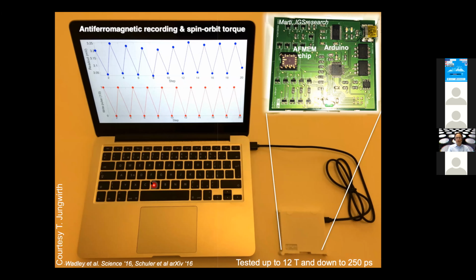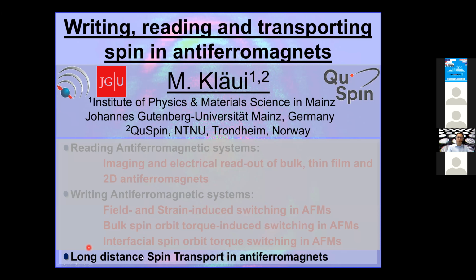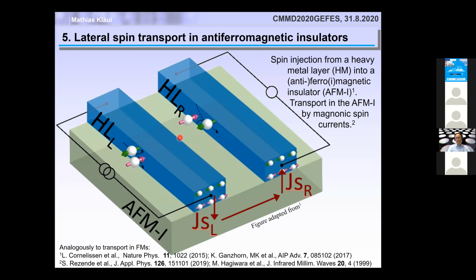And so the last 5 minutes, I'd just like to show you something about spin transport in antiferromagnets. And what we want to do is we would like to transport information over long distances in ideally insulating antiferromagnets. And the reason is that a lot of the power consumption in typical semiconductor devices is due to the current flowing in the vias, in say the copper vias, and that leads to ohmic losses. So if you replace the information by electron motion by the information transport, for instance, by magnons, so spin waves, then this might be saving a lot of energy.